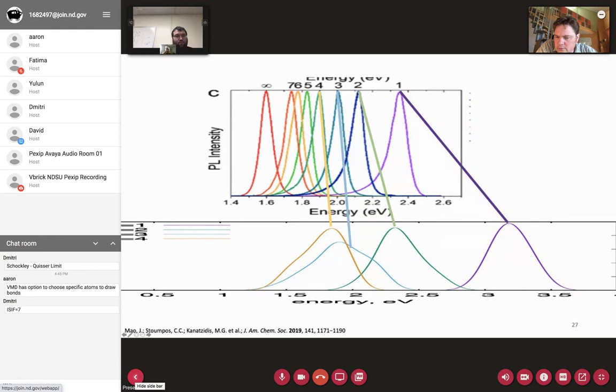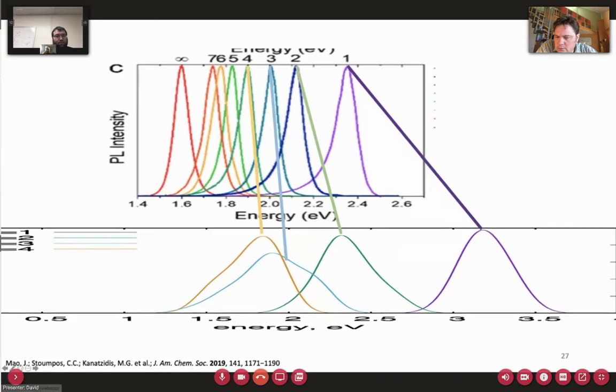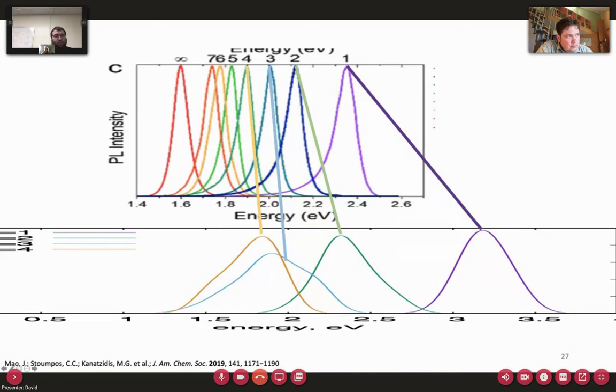I guess for the quantum dot model that I worked on, it was substantially wider. But then again, experimentally, they don't look at models as small as the one we were looking at. So it's not a direct one-to-one comparison. But usually in experiment, they see the smaller the quantum dot, the wider the full width half max. Okay. So qualitatively, our MDPL procedure kind of followed along with what's seen in experiment.